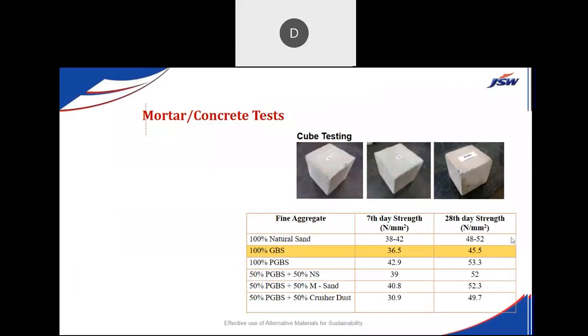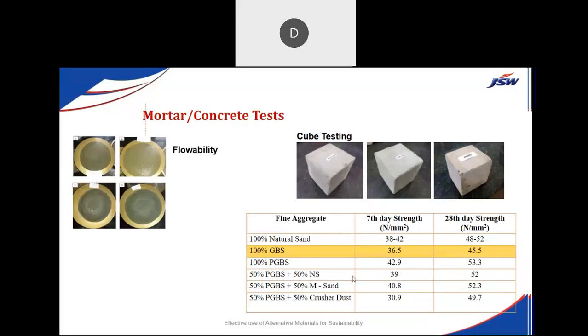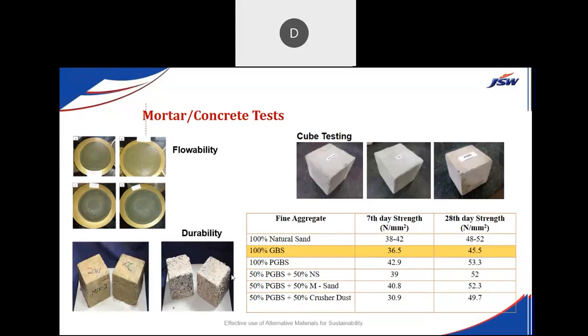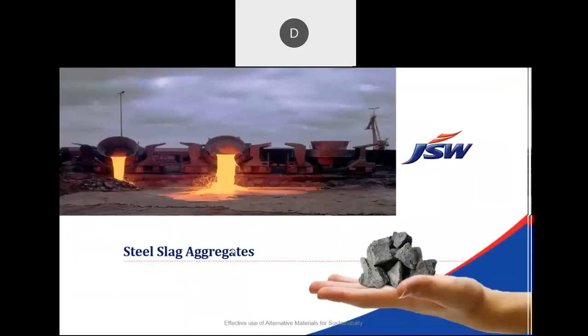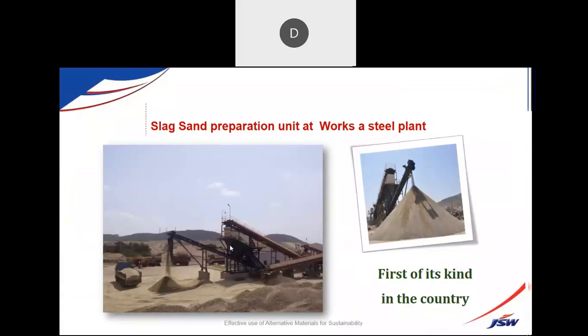strength parameters, 7 day, 28 day strength, and various replacements we have done with the natural sand. So you can see the 100% replacement of GGBS sand also giving similar strength like natural sand. Maybe a 1 or 2 MPa variation will be there, but it's similar to natural sand and much superior to the M sand. We have checked for durability, and checked for workability. This is what we have established, the plant at Bellary. Close to 50 to 60,000 tons per month it's going. Per day, we are doing about 1,500 tons of sand manufacturing.